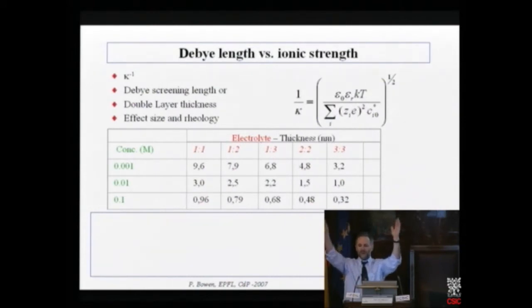So it's a little bit like an osmotic pressure. If we have solution away from the particles, which is lower concentration, and high concentration at the surface, we try and dilute that, like an osmotic pressure, and this pushes the particles apart. So it's not a direct classic physics vacuum electrostatic interaction, but it is dependent on the surface charge.